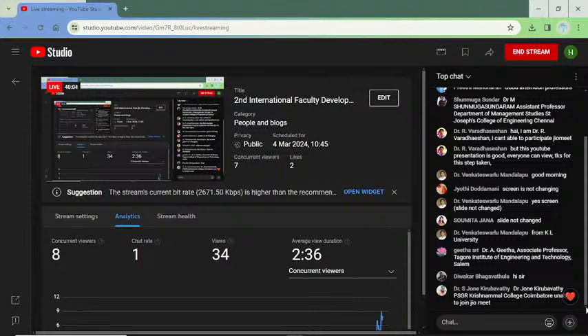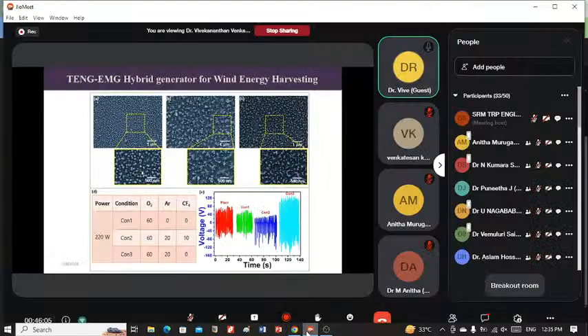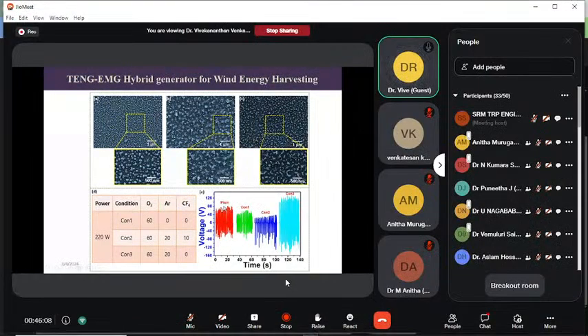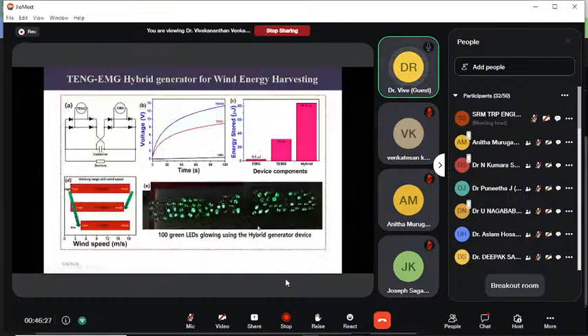So here we created a surface roughness to multiply the output of the Kapton film which we used, using the inductive coupled plasma etching technique, where you can see A, B, and C figures showing how we have created a micro roughness here. Each of these has a 1 centimeter, 1 micrometer, and a 500 nanometer scale bar also attached here. You can see a nano sized micro roughness has been created throughout. Condition 1 we use only oxygen. Condition 2 we use oxygen and argon, and condition 3 we use oxygen, argon, and CF4. We see that oxygen and argon could create a very good micro surface, leading to generation of very good electrical output.